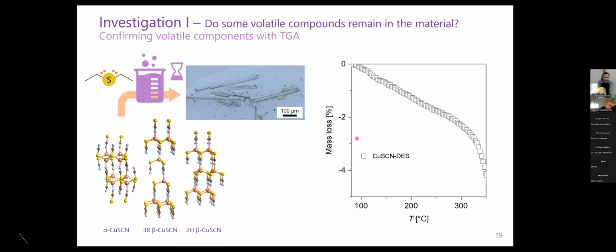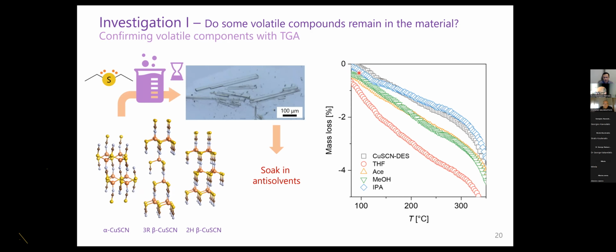Measuring the mass loss, we can see that this compound, the compound where the diethyl sulfides are fully coordinating with the copper, starts losing the ligands when we heat above 100 degrees Celsius. So after soaking in the anti-solvents, we were hoping the mass loss should be less, because we hoped we could remove the diethyl sulfide. But actually no, it's either the same or even more mass loss. That was already quite surprising, perplexing.